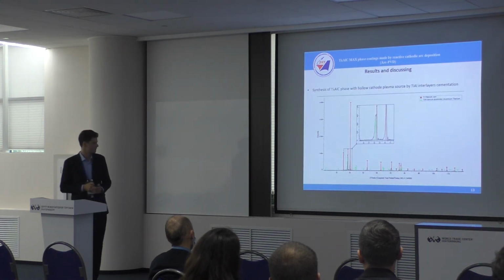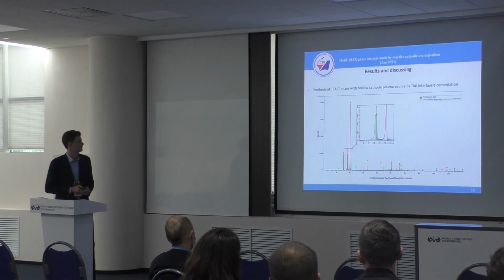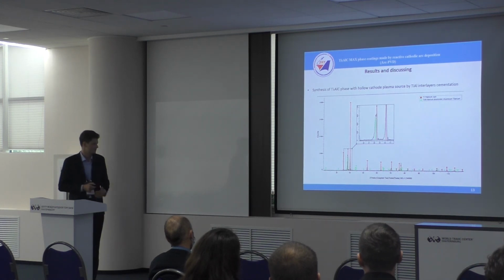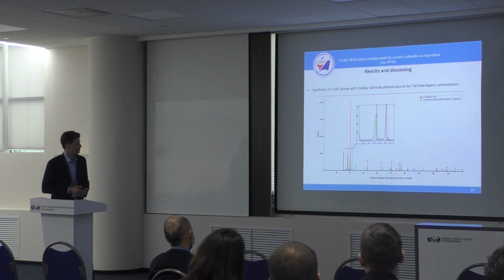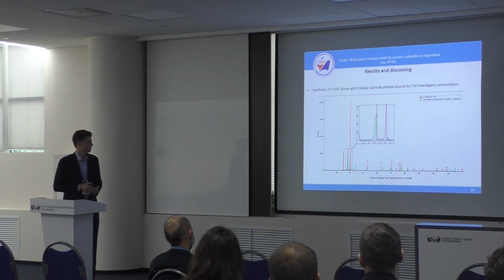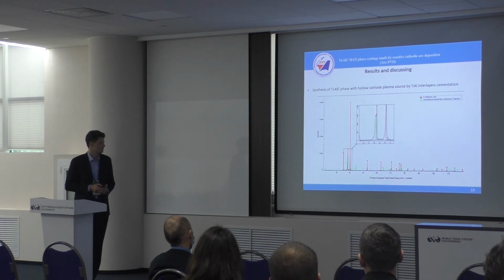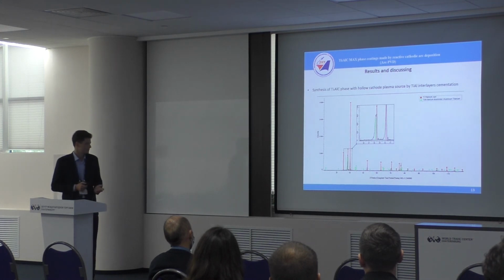Here we can see the X-ray pattern after cementation. Unfortunately, I must say that cementation is probably not the best choice to synthesize MAX phases. You can see no peaks of any carbides or MAX phases, just titanium and titanium aluminum intermetallics.